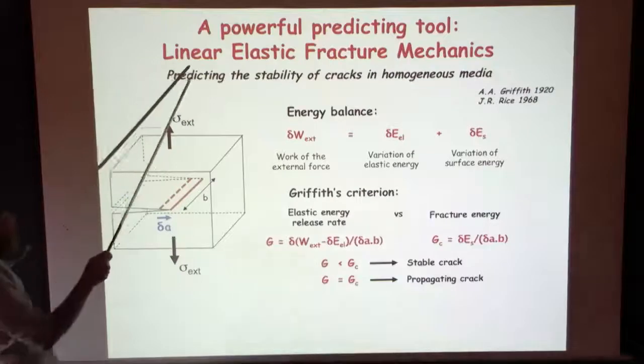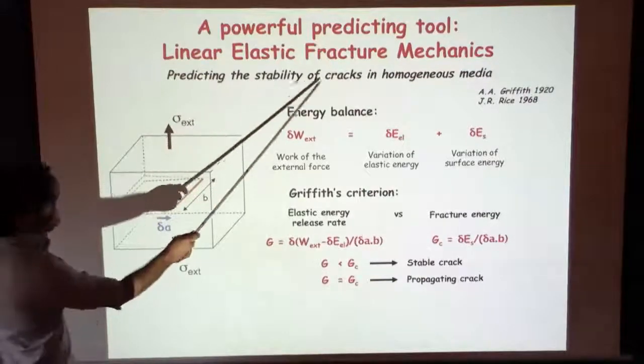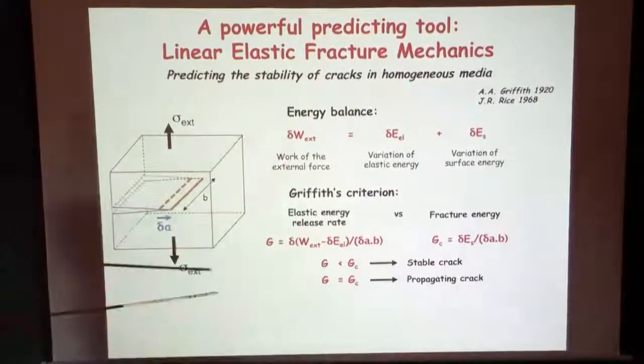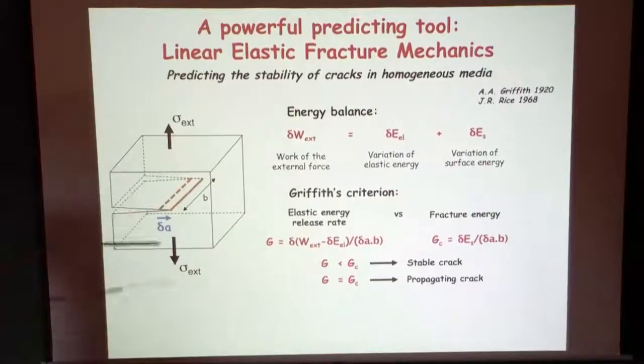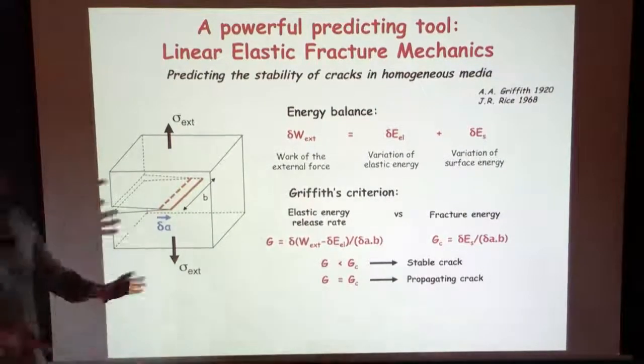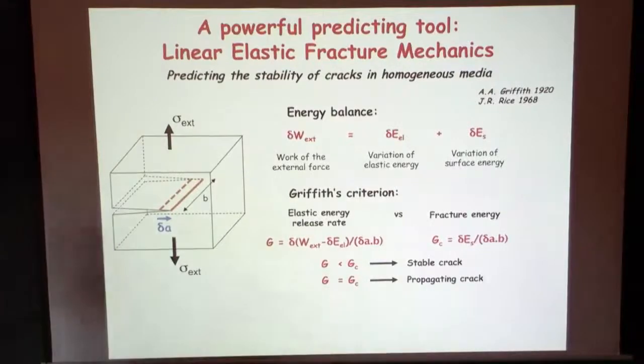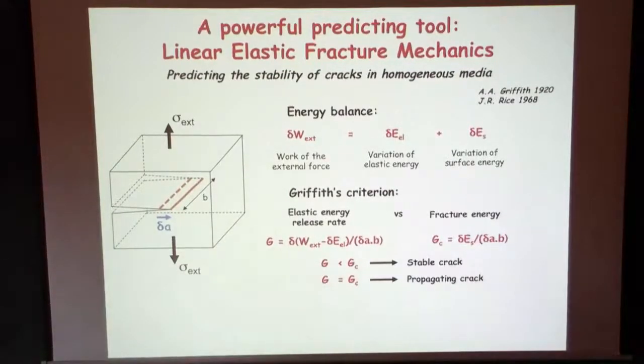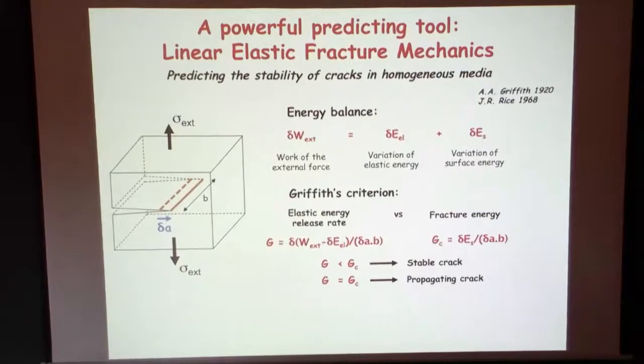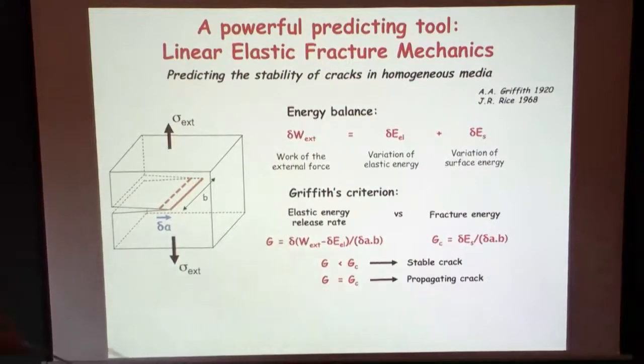Did I mention predicting the stability of brittle cracks somehow? This approach can fail if you have dissipation in the volume. But as long as it's confined to 10 micrometers or something, it's fine. That's quite big compared to atoms, it still works, right? Yeah, but in ductile failure you have the whole volume involved. It's the whole volume and it fails. But that's a good point, and we come to that.